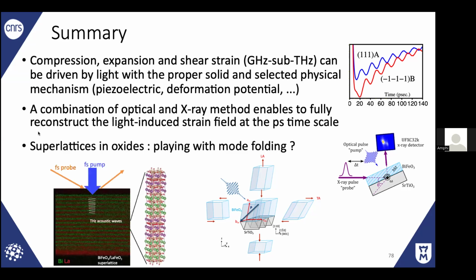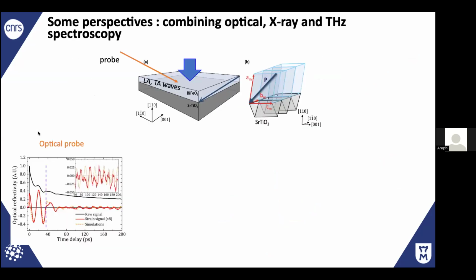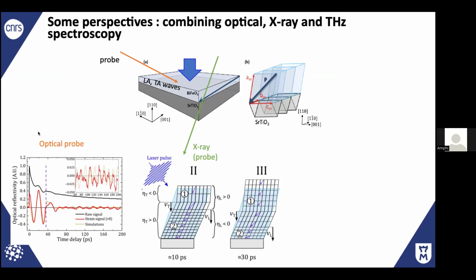Of course, if you combine optics and X-ray, you can get the absolute value of the strain you induce. And with superlattices, finally, our recent work showed that you can play with the mode folding if you consider that the superlattices are not simply a superposition of chemically different layers, but due to long-range ferroelectric order, you can have a double mode folding. So today I discussed optical pump probe, and X-ray.